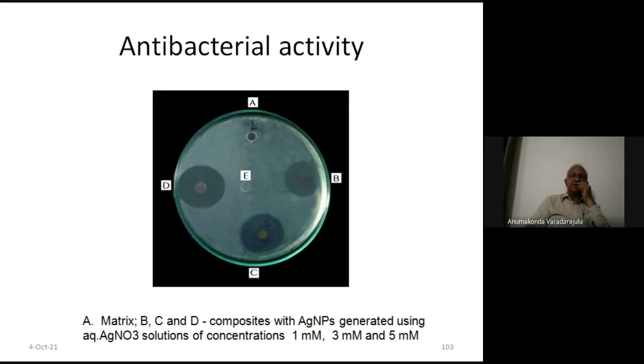Later, we tested the antibacterial activity. The matrix did not show any antibacterial activity. This is a matrix film, but no clear zone was formed. Whereas these are the nanocomposite films of 1 mM, 3 mM, and 5 mM silver nitrate source solutions. And you can see that clear zones were formed with increasing diameter, with increasing source concentration here. So these showed very good antibacterial activity.